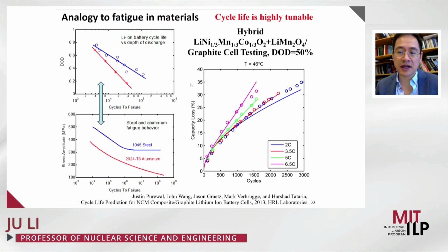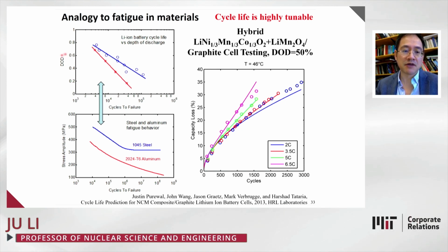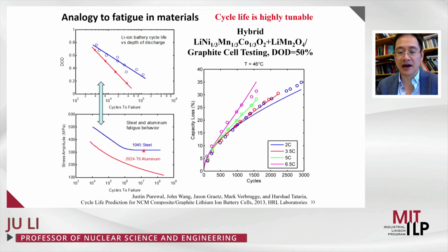And there is a very interesting analogy to fatigue in materials, because it turns out that batteries, when you only use a low depth of discharge, can have exponentially longer cycles to failure. So the horizontal axis here is the cycles to failure in log axis. So you see that if you only use 20% of the battery, then you really can get exponentially longer cycle life, which is analogous to the fatigue life of some kind of steel. And there is also a very nonlinear dependence on the charging rate as well. And so you have this very nonlinear envelope of battery characteristics.